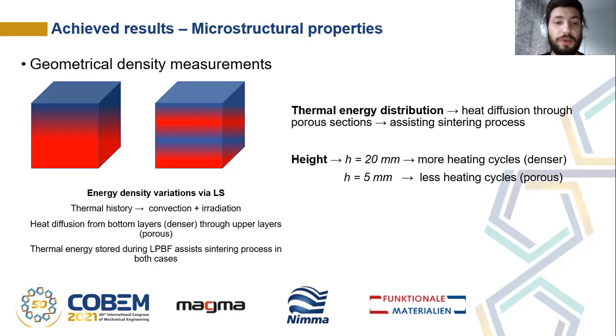The heat diffusion from the denser layers throughout the porous ones can lead to this condition, where porosity is eliminated instead of retained. The thermal energy stored during the laser powder bed fusion process assists the sintering of polymeric particles. This is evidenced by the reference samples with different heights. 20 mm height samples were exposed to more heating cycles than the 5 mm height samples, leading to different porosity levels under the same processing conditions.